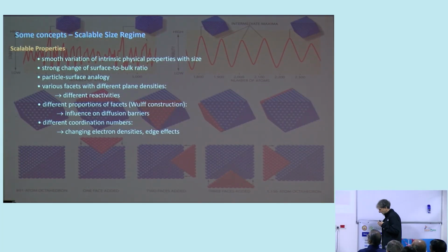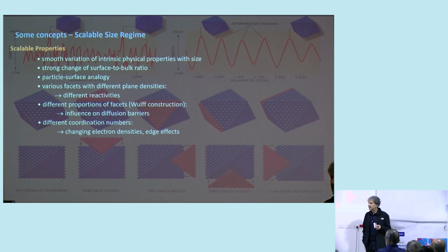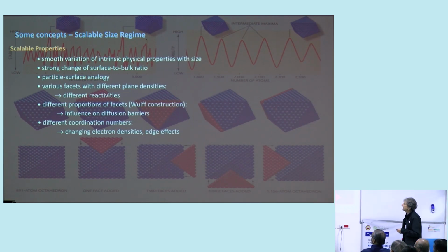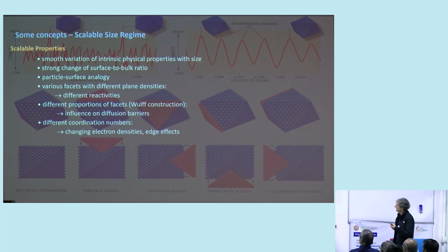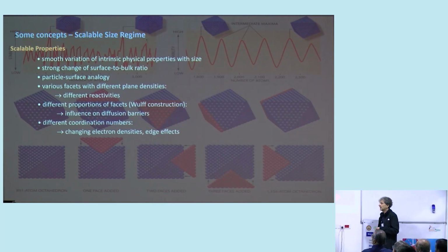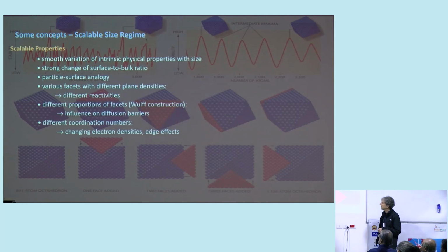And so if we try to summarize some concepts, the guiding principles of this scalable size regime, we can say that we have a smooth variation of these intrinsic physical and chemical properties as a function of size. So we expect also not very drastic changes in the catalytic properties. But of course, we have a strong surface to bulk ratio. And so if we see increased reactivity in comparison to bulk, it is mainly due to the surface to bulk ratio. Then, of course, as I explained, we have different facets with a given reactivity, we have this Wulff construction, which can influence these diffusion barriers. And of course, on the surface, we have different coordination numbers, which can influence the catalytic properties.